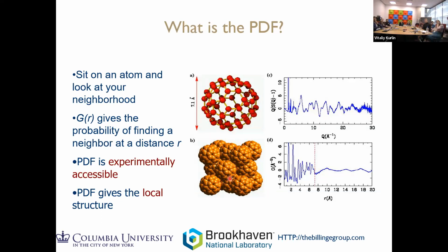It turns out I get a triangular line shape for a hollow sphere of uniform density. And then if I look at this sphere distance, it's peaked at around 10. And it's FCC, so the second neighbor distance is root 2 times 10, the third neighbor distance is root 3 times 10. So I expect a second neighbor distance of 14, and a third neighbor distance of 17. And so this thing out here is actually telling us about the packing of the molecules.